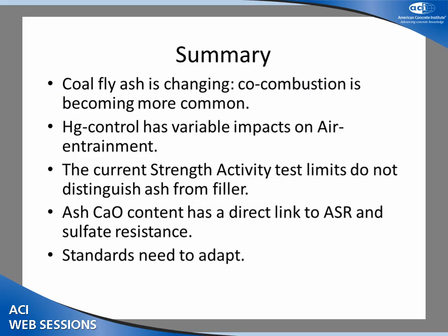Okay, so in summary, coal fly ash is changing because of the environmental regulations. Co-combustion is becoming more common. The powdered activated carbon issue for mercury control is becoming a bigger issue. The current standards, at least here and in Canada, don't distinguish ash from fillers, and that's an issue. And the calcium oxide content, I think, has a more direct link to some of the durability issues that we're concerned with in the use of ash in concrete. And I think the standards need to adapt to those changes if they want to remain relevant in the marketplace. So I'll leave it with that. Thank you.